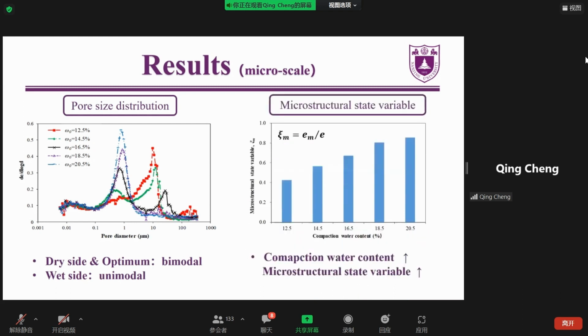Moreover, a simple microstructure state variable is adopted to quantitatively describe the microstructure of the samples. It can be found that with the increasing compaction water content, the microstructure state variable increases, which means a less aggregated structure of the clay particles.